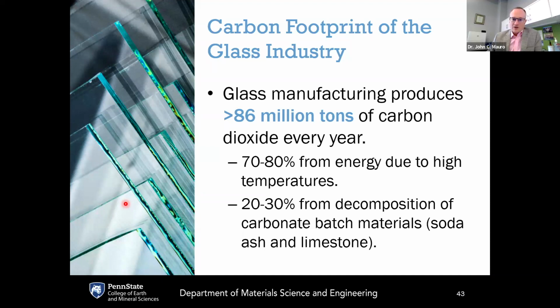So the glass industry still produces over 86 million tons of carbon dioxide each year. This is predominantly due to soda lime silicate glass. About 70 to 80% of that is due to the energy consumption from the high temperatures required to melt soda lime silicate, which is about 1450 to 1500 degrees C. The remaining 20 to 30% is from decomposition of carbonate batch materials. It's called soda lime because two of the main ingredients are soda ash, which is sodium carbonate, and limestone, which is calcium carbonate. When they're melted, they first decompose into oxides. When the carbonates decompose into oxides, they release carbon dioxide in the process.